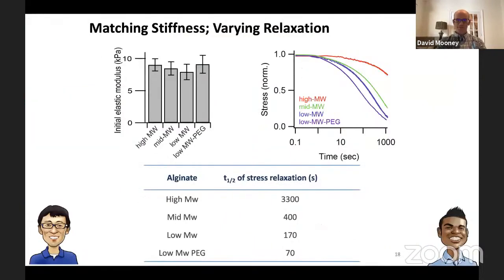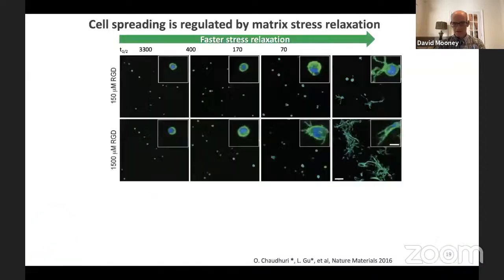So here's just an example of a group of hydrogels that Ovijit Chaudhuri on the right, who's now running his own lab at Stanford, and Luo Gu, who's running his lab now at Johns Hopkins, demonstrated a few years ago, where you can see from the top left that these four gels all have very similar initial elastic moduli. But on the right, you can see that they have varying rates of stress relaxation, which we've characterized by the half-time for stress relaxation on the bottom. And you can see that we get a couple orders of magnitude variation in the stress relaxation behavior while we keep the moduli similar or constant.